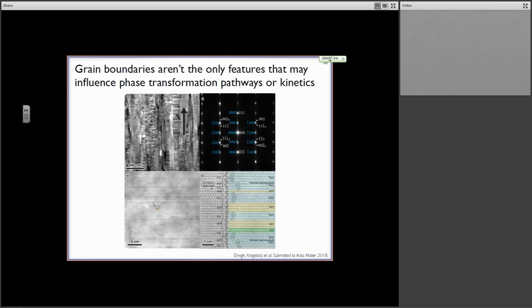You can see down here in B, the contrast is a little bit higher resolution. You can see the contrast of some of these planar faults. They're very systematic. They're very well organized. The texture of these films is quite high. And there's consequences for this. In fact, what was really surprising to us is that this is a nickel-based alloy here, but it's not all face-centered cubic in its structure.